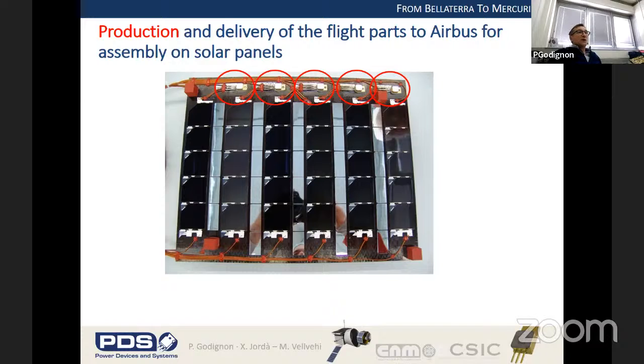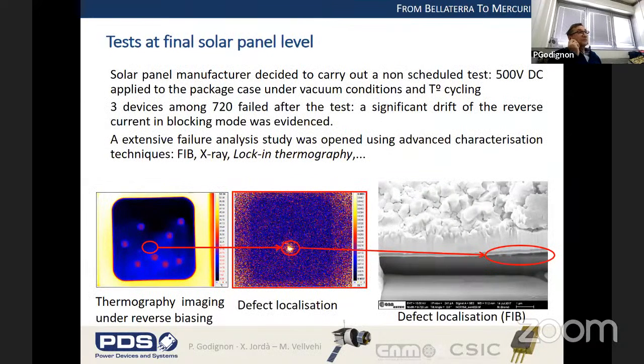So we were happy because our work was supposed to finish here, but we had a last issue, because the solar panel manufacturer made an extra test, which was not scheduled by the European Space Agency. They applied a high voltage on the case of the package and applied temperature and vacuum cycling. And after this test, they observed that 3 of the devices among the 720 which were mounted on the panel failed. So it was a big issue, a big panic, let's say, since this was unexpected but quite important.